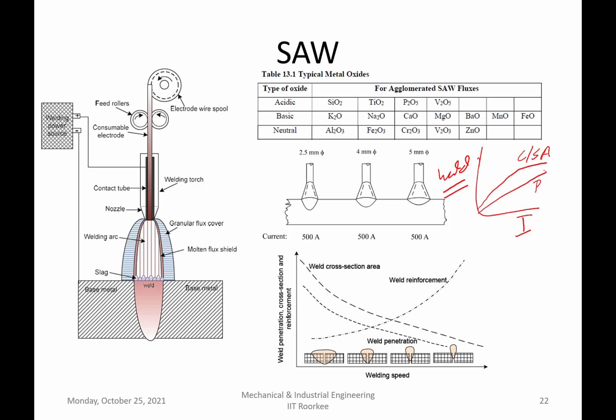If you maintain the welding current and increase the diameter, what happens? The diameters are 2.5, 4 and 5. For a given current rating of 500 ampere, the penetration is deeper with the use of a small diameter electrode conductor, and the weld is narrow in width and deeper. On the other hand, with increasing diameter, the weld becomes wider and the penetration becomes shallow.